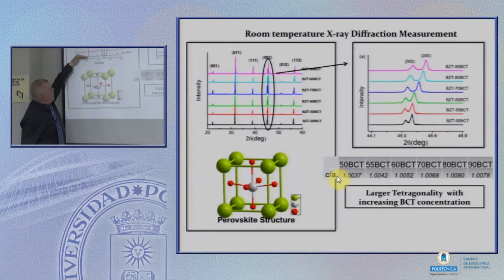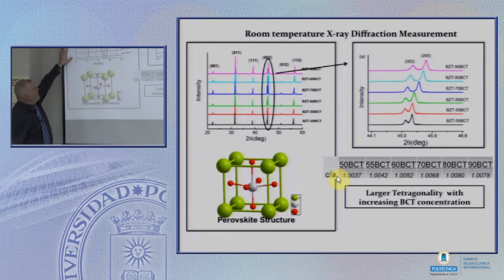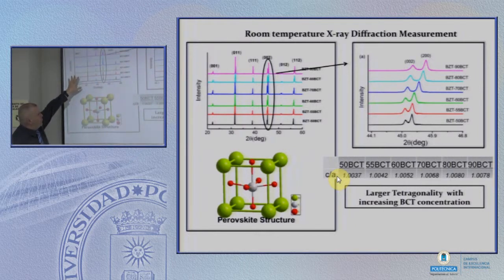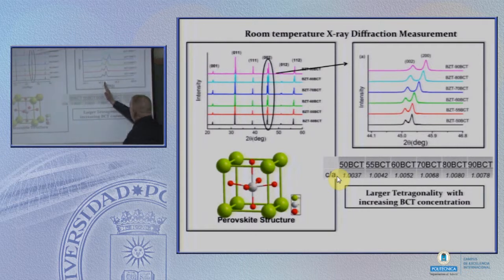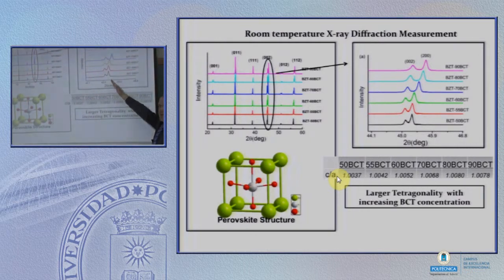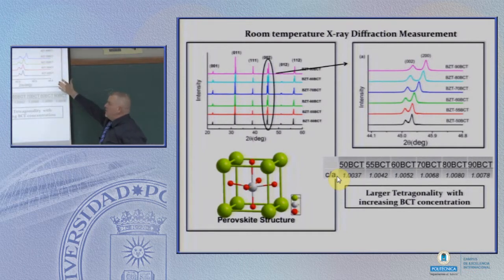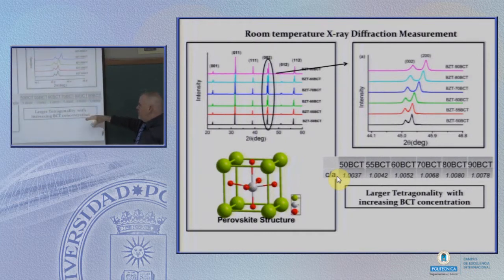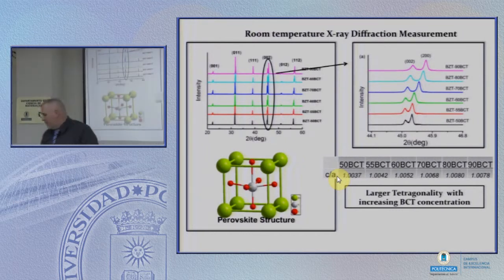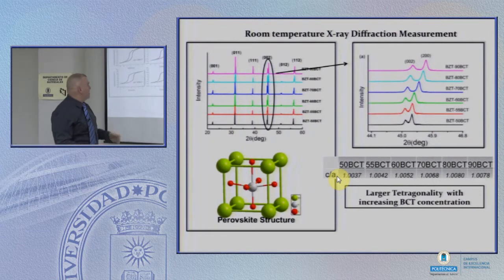So essentially, this is going from the center. This is 50-50 up to 90-10, right? And this is X-ray diffraction showing the results. If you look here, you can see the difference in the lattice parameters. That's due to the shift in terms of 2 theta. And you can see this characteristic 1 versus 2 for the left versus the right side for tetragonal material. So exactly the same thing that I showed earlier. These are materials in the unpoled condition. We got the lattice parameters for these, and looked at them for that whole spectrum. We also looked at the properties for those materials, and tried to understand them. This is the set of polarization loops.